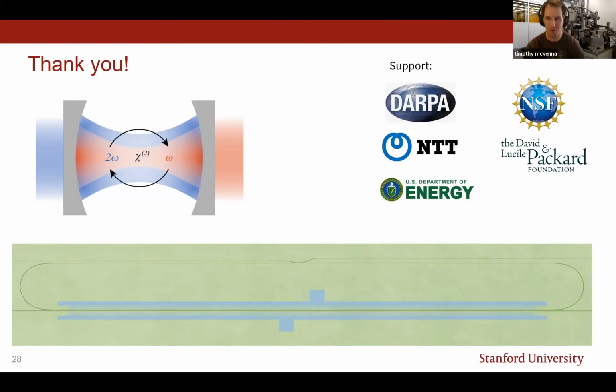Another thing that can be important is the fact that these waveguides are not single moded. In fact, at the second harmonic, there are many modes. So this can cause different types of mode mixing, which can reduce the Qs. If you couple to a lossier mode, you can reduce your Q a little bit, but it can also slightly push the frequency of these modes. That also can change what modes oscillate, because now you have disorder a little bit in the absolute frequency of the mode, but also in their Qs.